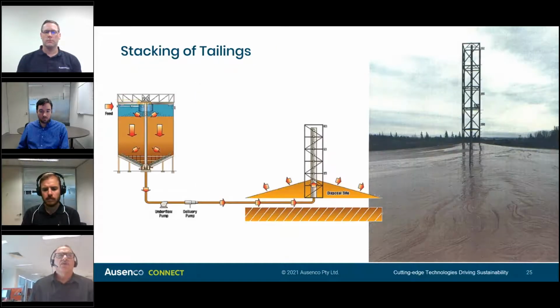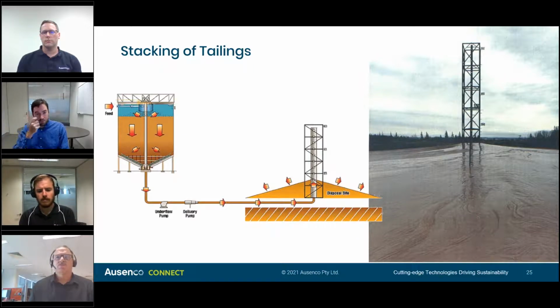Next. So the options of tailings has also been basically utilizing your thickener and then pumping this material into a central column discharge. In this particular instance, you can note that the thickened paste is deposited from above and basically falls down and creates a much steeper beach slope. In this case, you're probably looking at 4, 5, even possibly higher degree beach slope. But this is a very effective way of basically pumping your deposit without spending too much on filters.